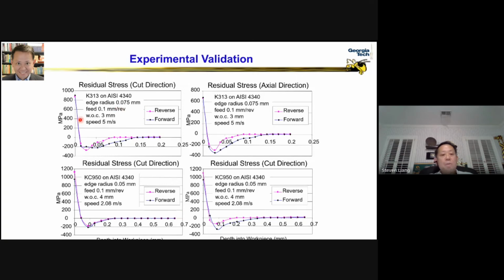And this is a validation of what we do. Our sponsor actually implemented the dark blue color residual stress distribution, but they did not tell us what process parameter was used to generate that. They gave us this dark blue line as the input, and we ran our program, which offered a combination of process parameters. They used that set of process parameters to do physical cutting one more time to generate the residual stress in the reverse process, the red line. They come out to be quite similar to one another.